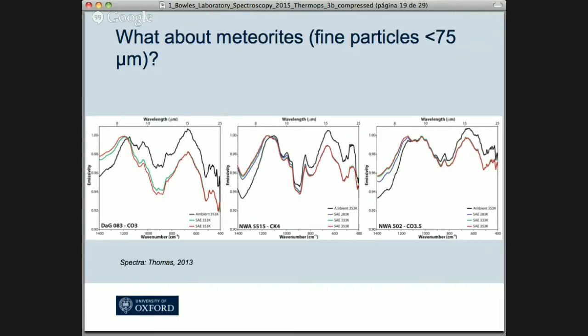So for example, with DAG-83, when we switched from ambient to simulated asteroid environment, so this was again sort of getting to Bennu-like conditions, we did see a spectral shift, and there are strong bands moving around and all that kind of stuff, like we did for the Moon. But for NWA 5515, it's much less pronounced. We see much less shift in the positions and strengths of the bands. And the same is true for NWA 502, which is very interesting. It probably has to do with essentially the intimate mixing that's going on, these much more complicated samples. And this is something that requires further investigation, but it's certainly of high interest in missions like OSIRIS-REx, I think.